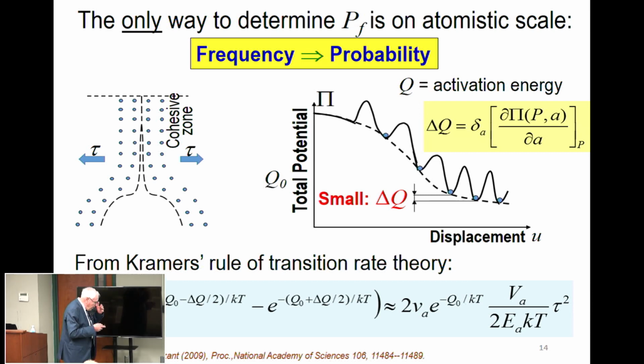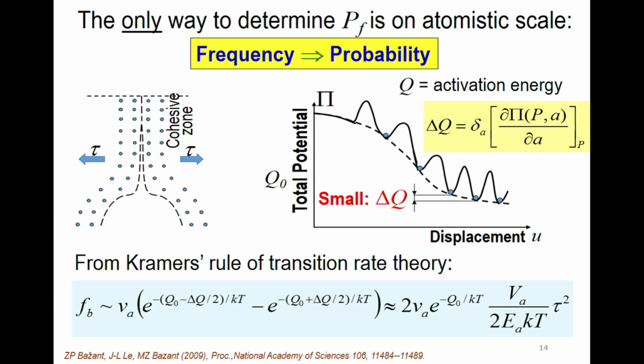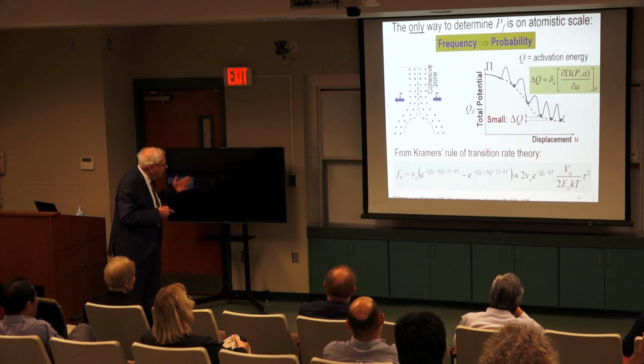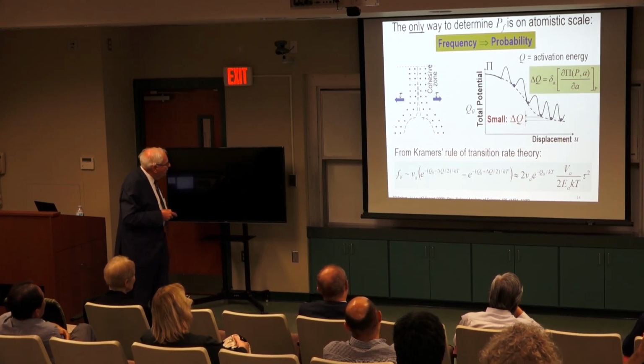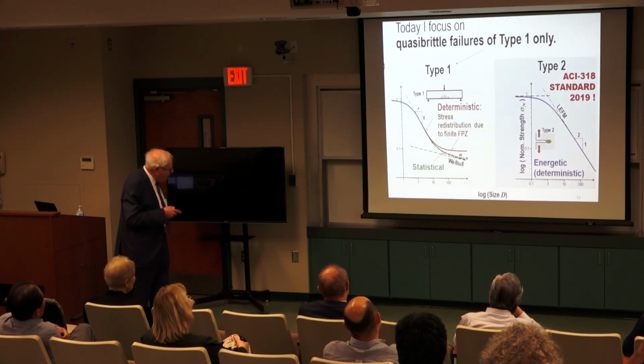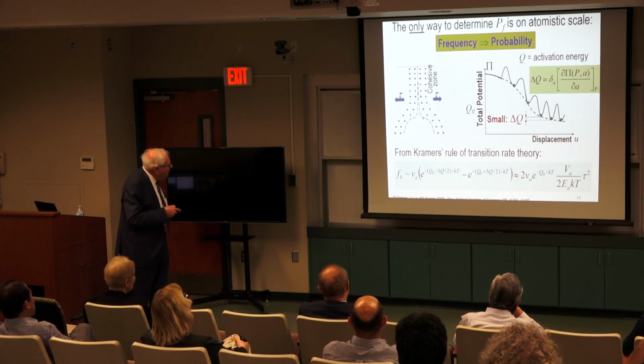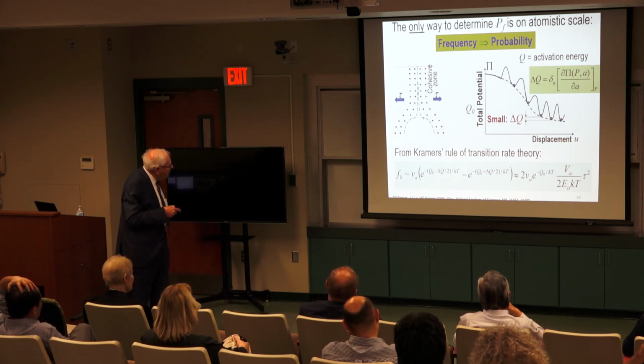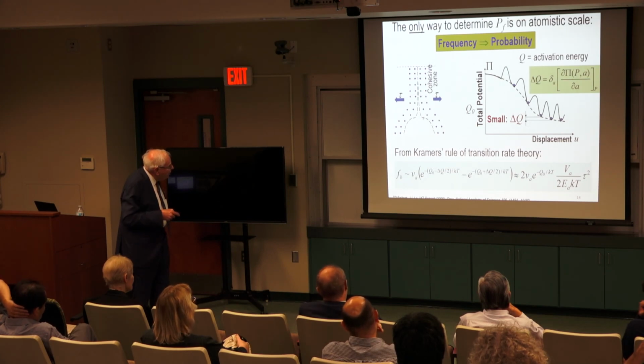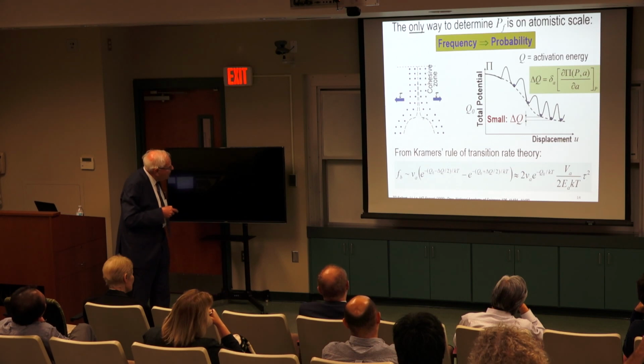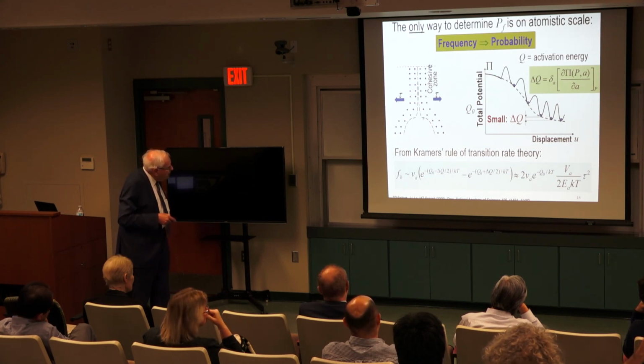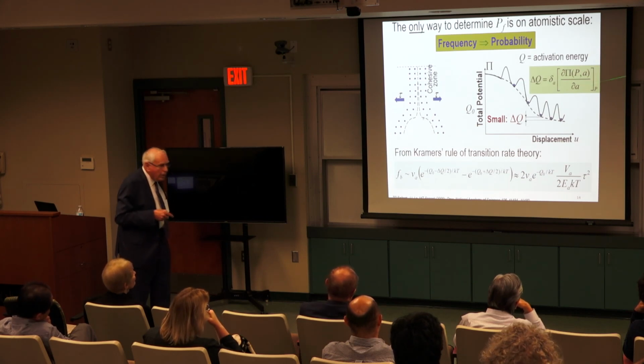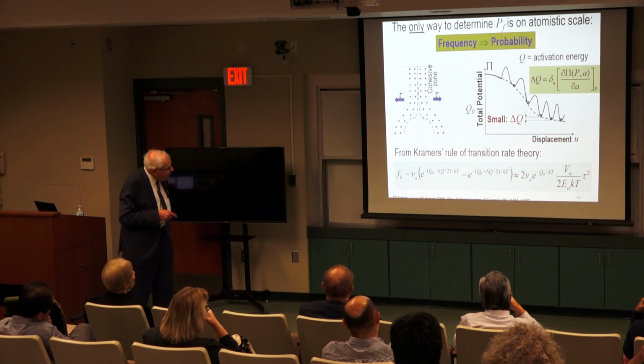That's the only scale. So we looked, that's a decade ago, at propagation of a crack through an atomic lattice. It's similar in disordered materials. Before you advance the open crack, it has to advance through the lattice by steps, obviously. So it's either here or there. And this discrete motion superimposes an undulating potential on a smooth potential which you normally derive for this nanoscale zone. So the total potential decreases as the displacement of the crack grows, and the main point here is that these ways to go down are numerous, in fact thousands maybe, so the difference between the valleys is very small.